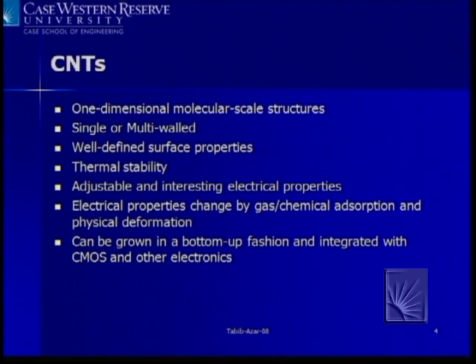So for those of you that may not know about carbon nanotubes, these are like graphite that are rolled back onto themselves. You can get them in single-wall or multi-walled versions, depending on how high a temperature you use in growing them. They're really easy to grow. You need methane, which is basically a cooking gas, and a catalyst, something like nickel or iron, in order to grow them at 700, 800 degrees centigrade.